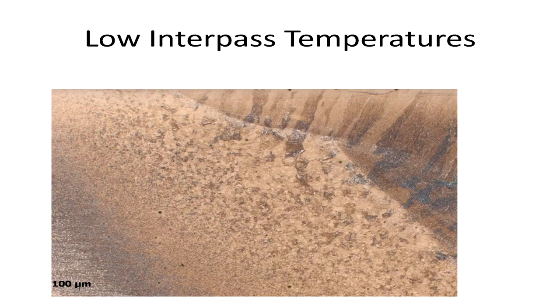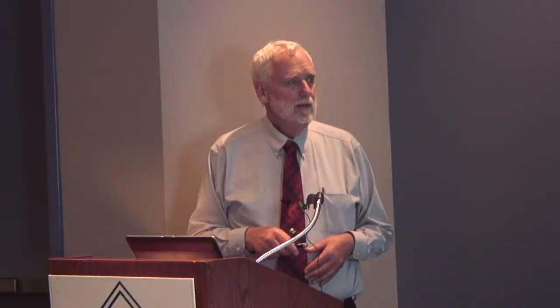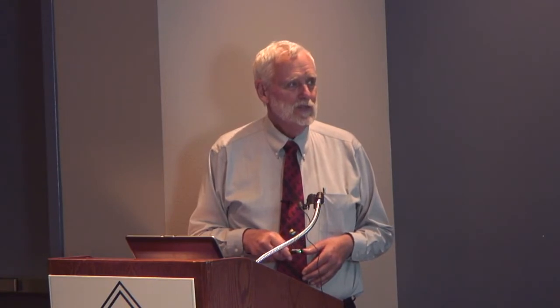All right, now watch this. This is really neat. That's the best practice one. See how small the grains are? When you overheat, the grains grow. I had 600 degree interpass temperature. See how they don't look burnt. Here's your base metal right here, and this got up to about 1,300, and here's your grain growth. And now you can see how the columnar grains grow out. This was the last pass right here. This was probably the first fill.